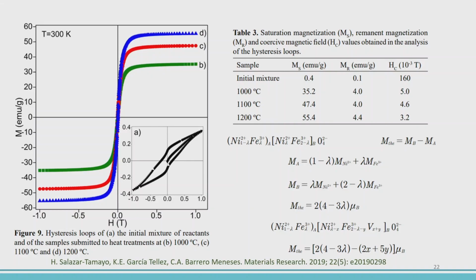But we notice the following. When lambda is equal to 0, we have a value of the theoretical M, but when lambda is equal to 1, it means that if we change from 0 to 1, then this M should decrease. But this is not observed, it's increasing. So again, cationic distribution cannot explain this behavior. Then we propose that perhaps there are vacancies, we put here B vacancies that are gradually filled as the temperature is increased.